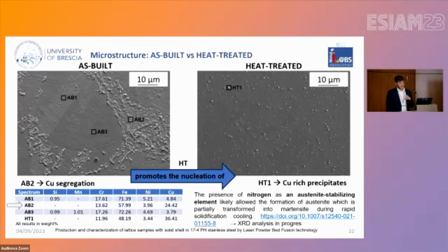And thanks to the heat treatment, this segregation solubilizes and promotes the nucleation of the copper. In fact, we can find in the second picture copper-rich precipitates. We analyzed, for example, one precipitate on the surface, and we found a higher amount of copper. In fact, we detected 36% more or less of copper. Moreover, the presence of nitrogen, as I said before, as an austenite stabilizing element, likely allowed the formation of austenite, which is partially transformed into martensite during rapid solidification cooling.